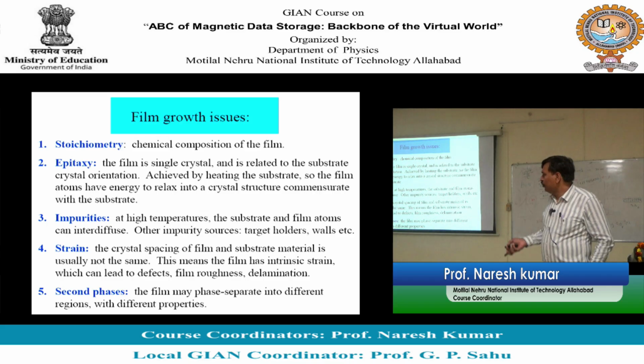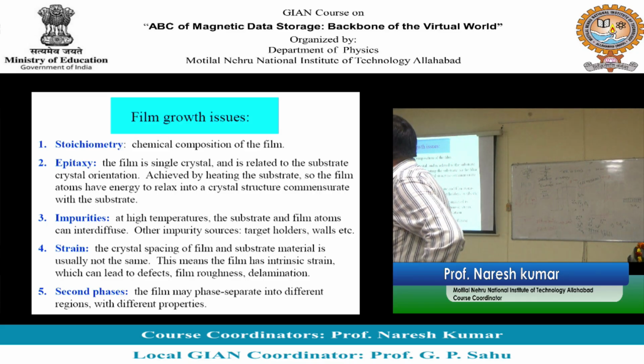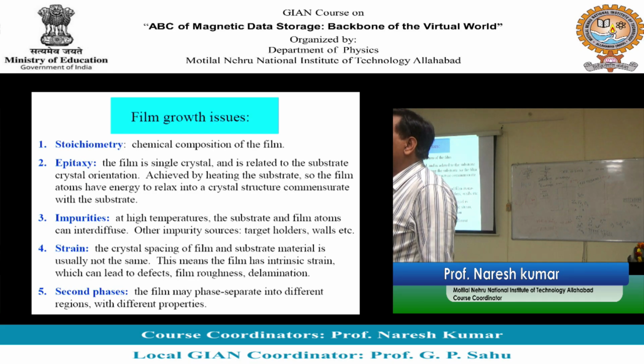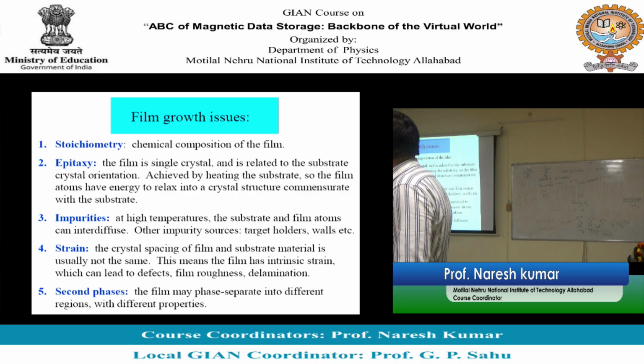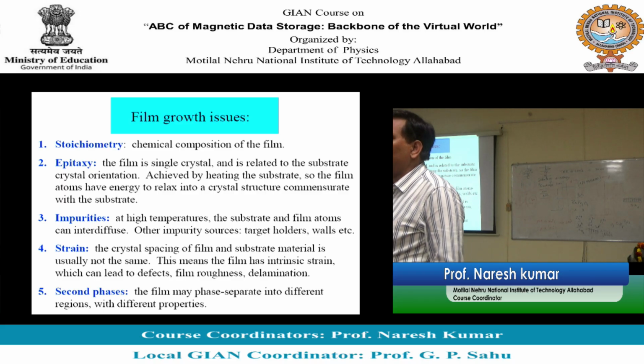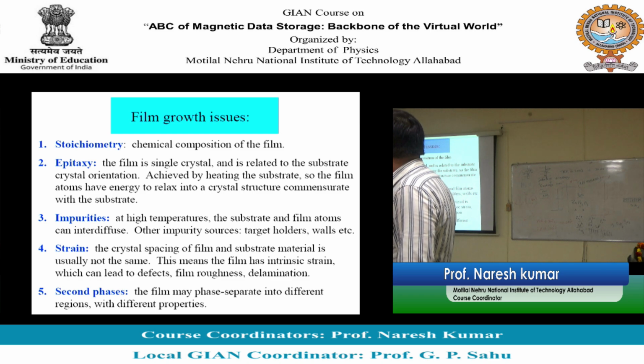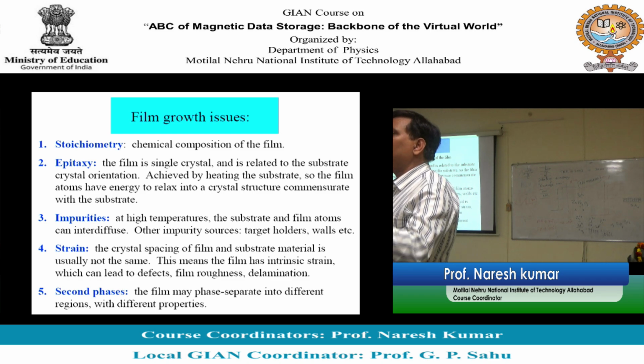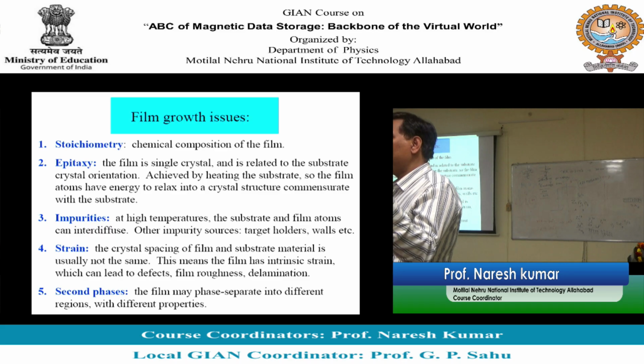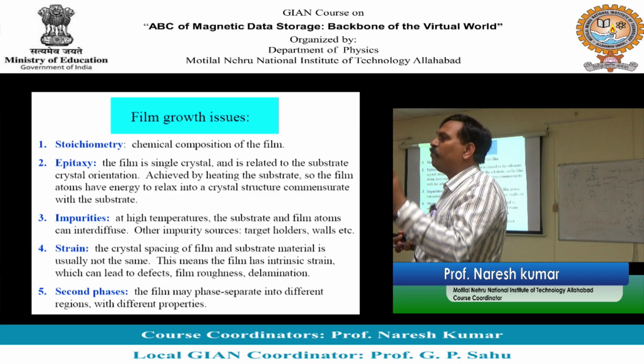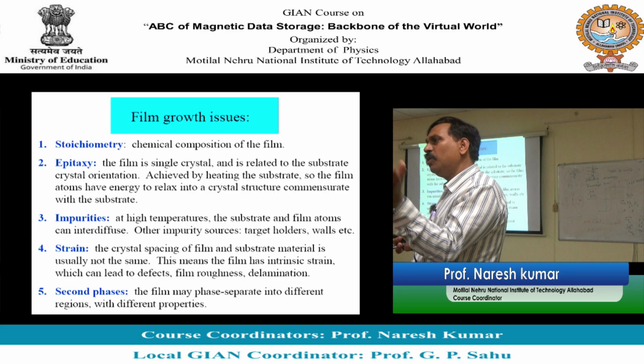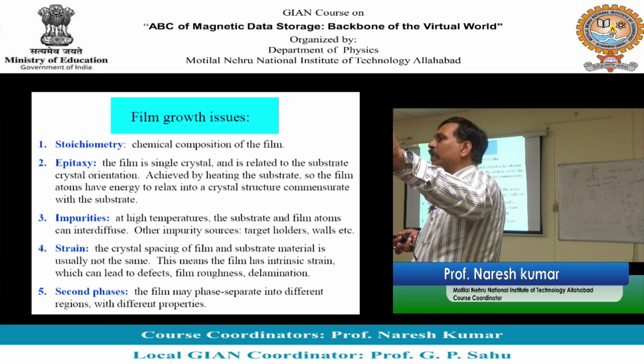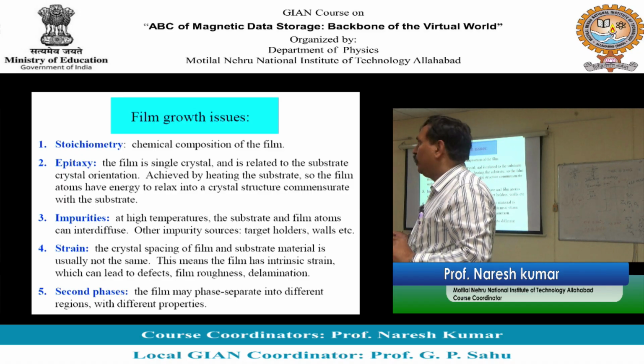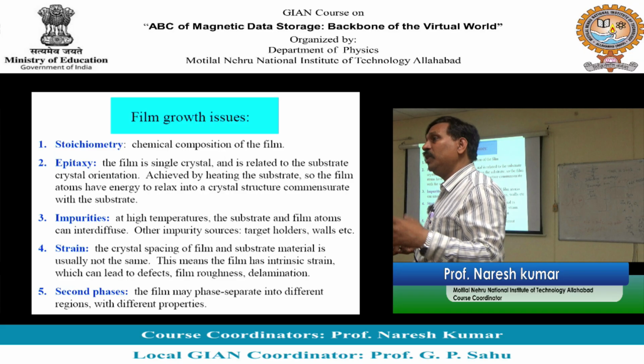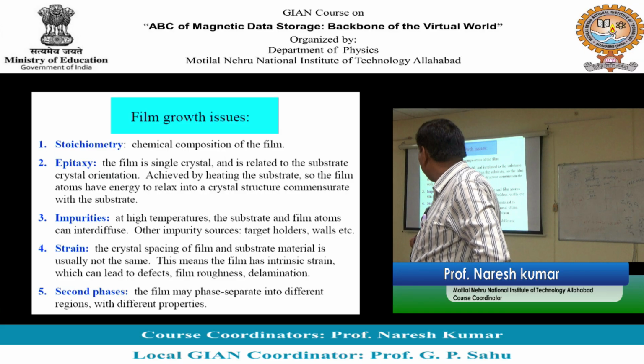Yes, these are a few issues that I think you all should understand. When we deposit films, there may be more than these challenges. These are the very important issues related to the growth of film. First is stoichiometry. If you are using a multi-component target, anything that has 2 or 3 compositions, and trying to grow films out of it, then it is quite possible that the composition is not maintained in the film. So whatever composition is there in the target, the same you don't see in the film. So if stoichiometry or composition is changing, then the film properties will change. So this is one of the very important things.